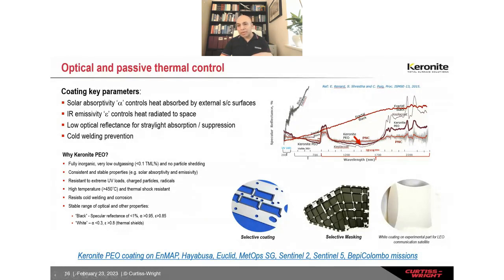On this middle one, I call it selective masking, because you are coating all of these deep pockets and thin ribs, but you also need to mask these shiny areas for electrical grounding purposes. So the electrolytic process gives you the ability to selectively either mask or coat. On this top picture, you can see the specular reflectance. The Keronite PEO coating has, in fact, very similar or even better performance than the competing coating in a wide range of wavelengths. And the other coatings are primarily paint-based systems, which are not good for a number of space missions.